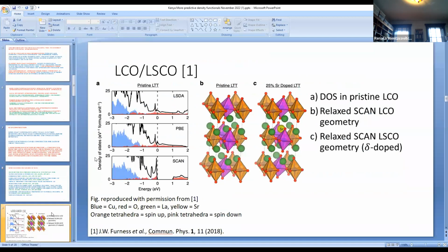On this slide, I'm showing you some results from a paper by James Furness and collaborators from 2018. They applied SCAN to the cuprate lanthanum copper oxide, or LCO, and also the doped cuprate LSCO, in which some of the lanthanum atoms are replaced by strontium atoms.